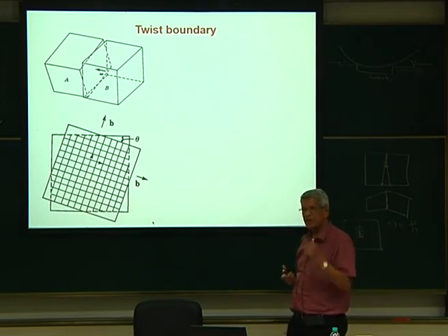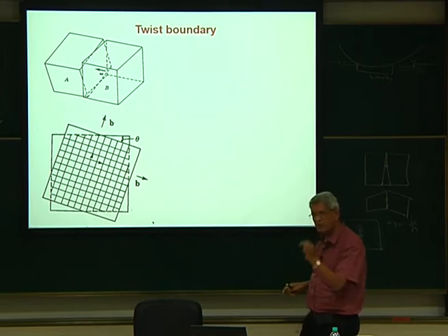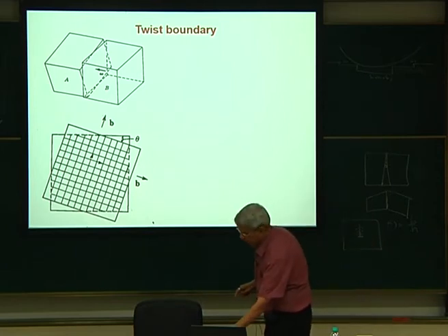Because of this, one set of dislocations cannot form a twist boundary. We require one and another one opposite. Both together decide the equilibrium position. You will always see that a twist boundary has two sets of dislocations perpendicular to each other.